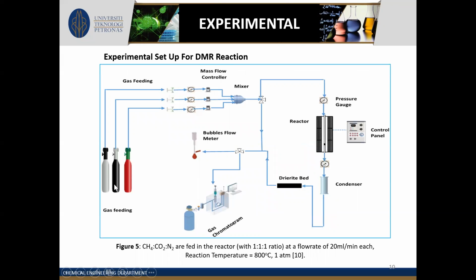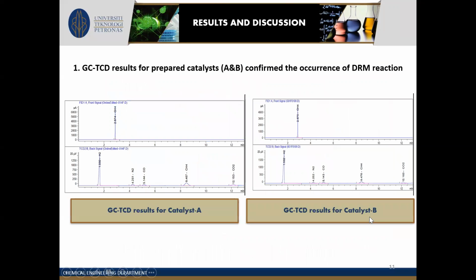This is the experimental setup which has been used: the gas feeding section, the reactor section, and the analysis section, that is the GC section. In the results and discussion, we can see the different peaks for hydrogen, carbon monoxide, nitrogen, methane, and CO2 in the exit stream for both catalyst A and B, which confirms the occurrence of the dry reforming reaction.